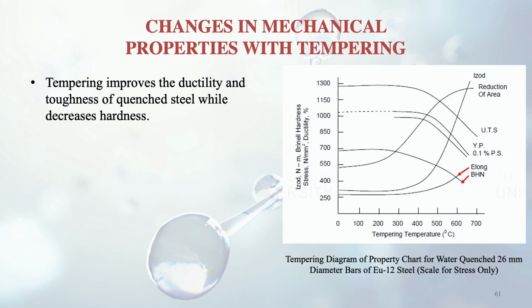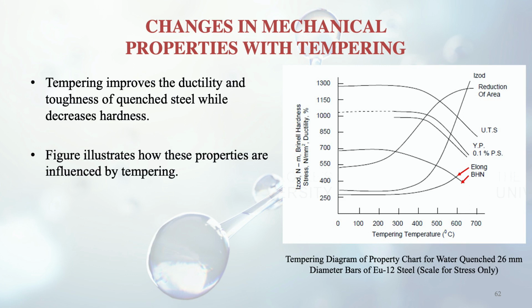We learnt about the tempering process, and now what benefits it gives us. It improves the ductility and toughness of the quenched steel and decreases the hardness. So two things: ductility and toughness increase and hardness decreases. From this curve you can see the tempering temperature is on the x-axis, and different things like the ductility measurement, impact strength, yield and ultimate tensile strength are on the y-axis, all given in terms of stress scale only, meaning Newton per millimeter square. From here you can see Izod is mentioned in the graph.